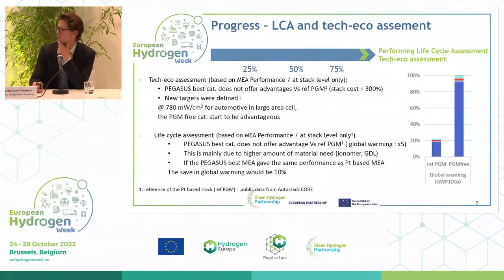Then we performed techno-economic and life cycle analysis of our materials. And the conclusion was not so good. We expected a better conclusion, but the conclusion is the conclusion. In fact, even if we do not use platinum at the cathode side with our MEA, we cannot compete with conventional MEA, either on the cost, because we need to put more cells into the stack to compensate the low performance. So it means that at the end, the cost of the stack is higher.